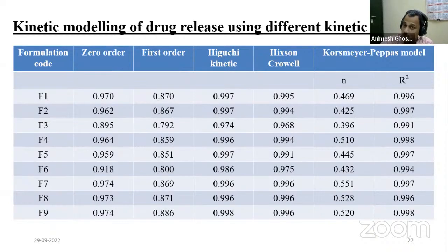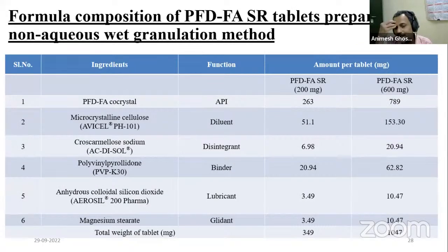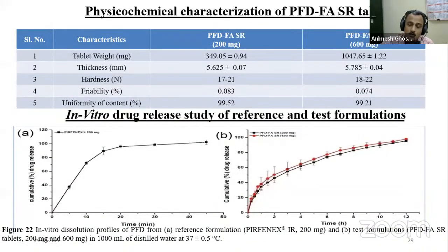That was actually our hypothesis, that if we can reduce the solubility, it will be converted into Fickian diffusion. It also obeys this model, because the n value should be less than 0.4 or 0.45 in the case of a cylinder. It is nearly about 0.4 to 0.5, so we can say it is following Fickian diffusion. After that, we have studied the in vitro release study.